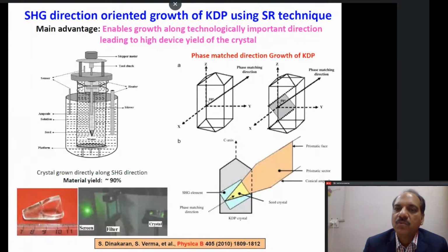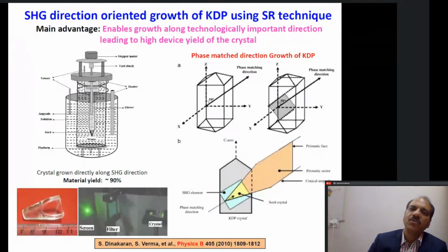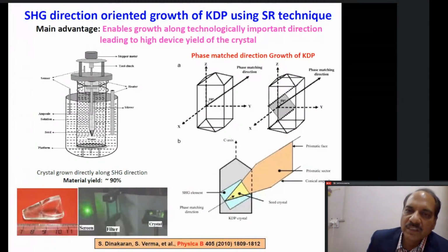I would say we must think to devise new technologies which can increase this usable volume. So what we thought was, why not use a seed directly oriented along the phase matching direction, put it inside a cylindrical chamber, with the axis of the cylinder along the phase matching direction, and let it grow along that direction. This cue was taken from the work which Ramasamy and his collaborator Professor Sankaranarayanan did, and you now know about this SR technique, the Sankaranarayanan-Ramasamy technique of growing crystals.